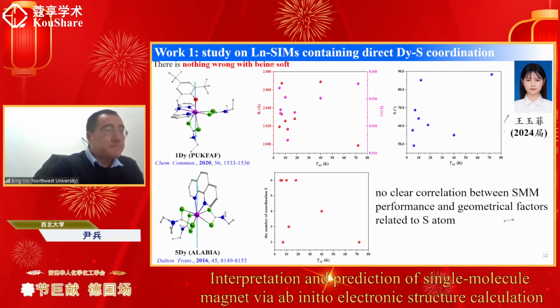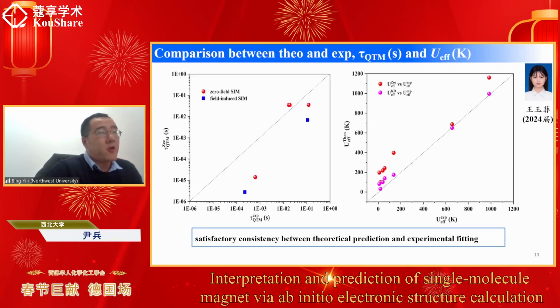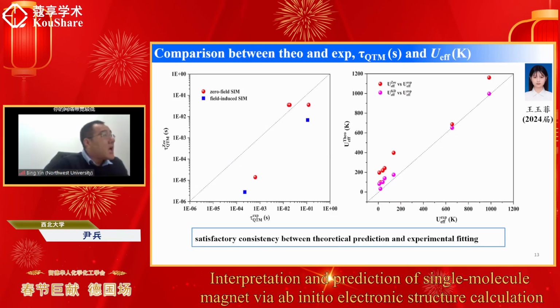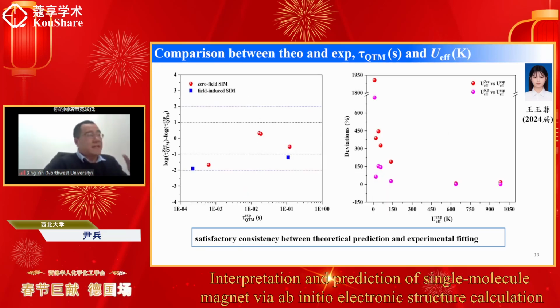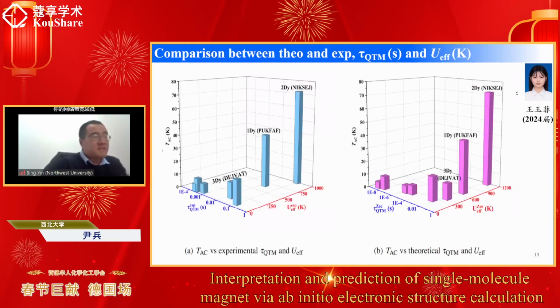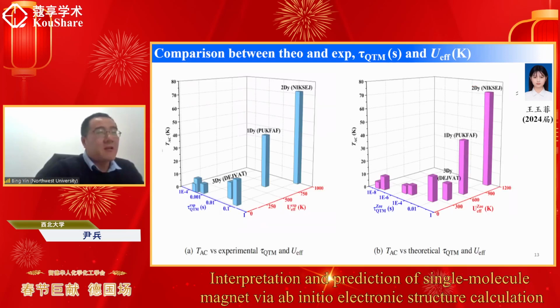And we compare our computed QTM time as well as anti-barrier with experiment, and we found a satisfactory consistency between theoretical prediction and experimental fitting. And the deviation is acceptable. And we also found that the system showing the best single-molecule magnet behavior is just the system which has the longest QTM time and the highest anti-barrier, irrespective of theoretical values or experimental fitting values. That means our proposed consensus criterion is workable here.